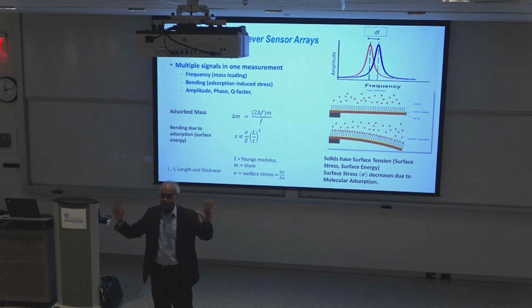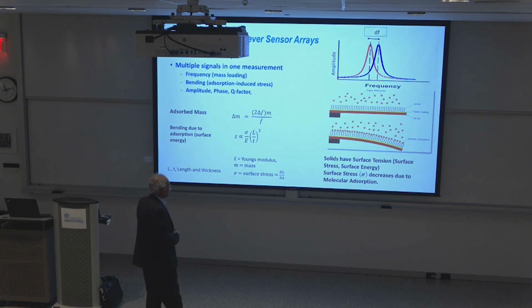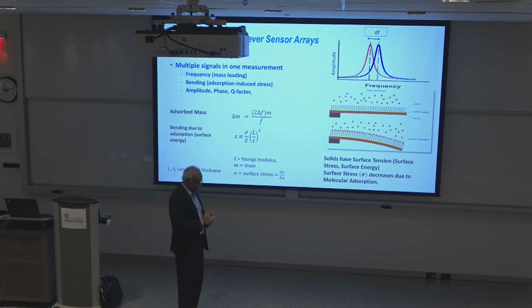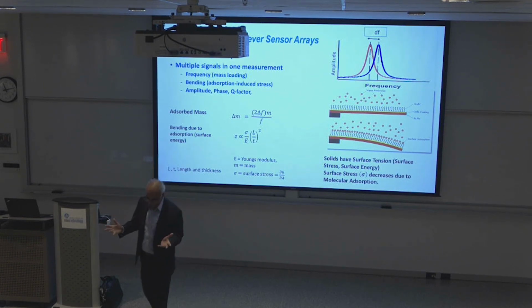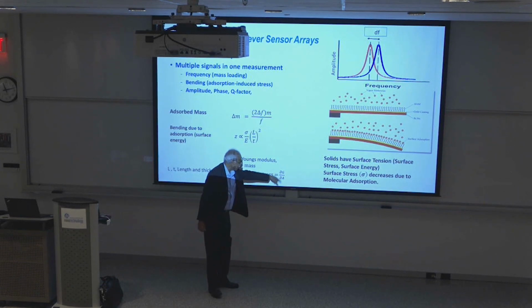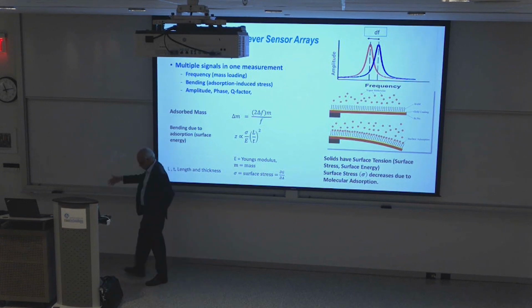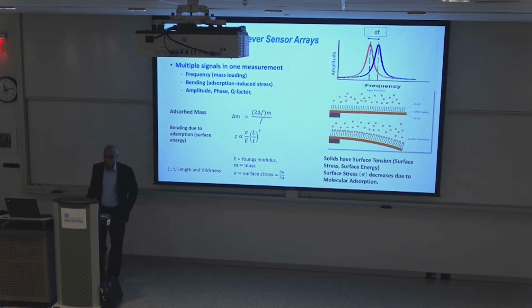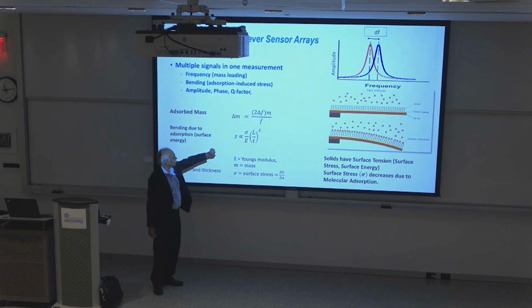It has nothing to do with gravity. You know, solids also have surface tension, what we call surface energy, basically joules per meter squared, which is nothing but the Gibbs energy per area at constant temperature and pressure. In addition, we also see changes in the amplitude, phase, and Q factor. But the first two, frequency and bending, are the easiest to detect at this time. And the equations are very simple. I can simplify this. Of course, you can add more and more.